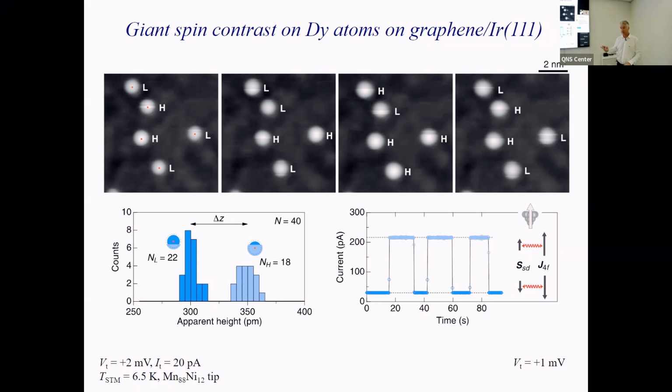Okay. So for me, it's basically such that if you have a contrast of 5 picometers or 2 picometers, the spin polarization must be such and such in the external shells. And if you have this contrast of 50 picometers, the spin polarization must be pretty high. So according to this, holmium and dysprosium should have a very small spin polarization, only 10%, 20% or so of electron transfer. And this one is an extreme example where almost a full electron is transferred.